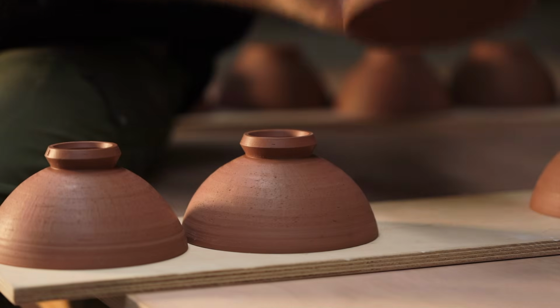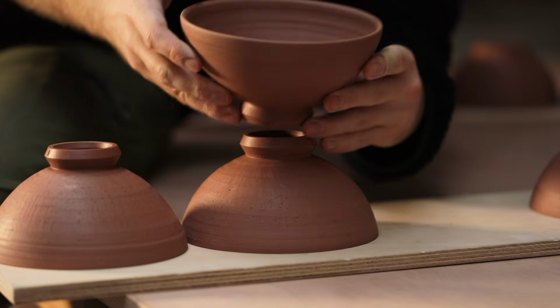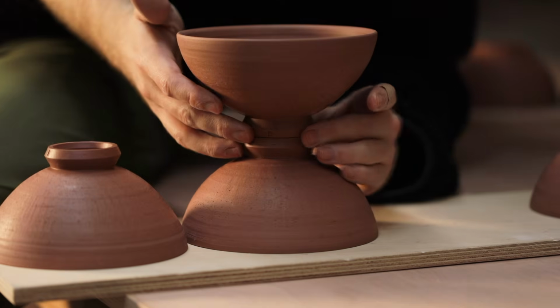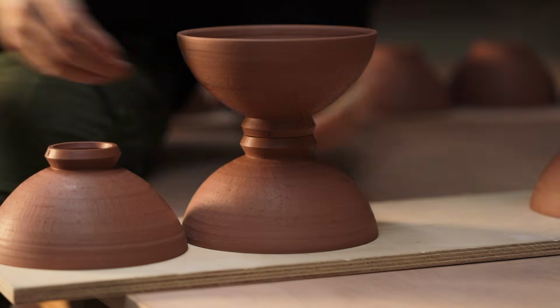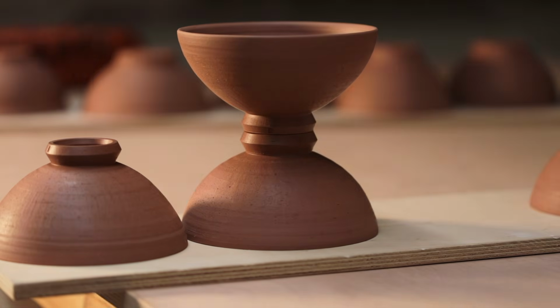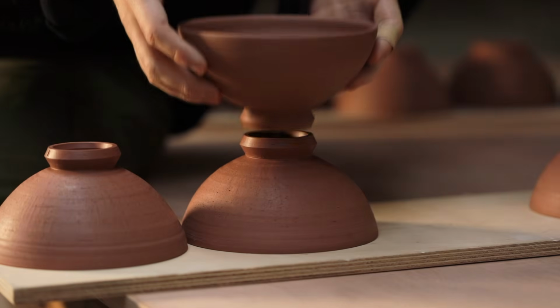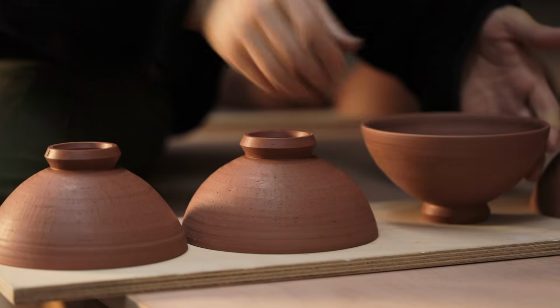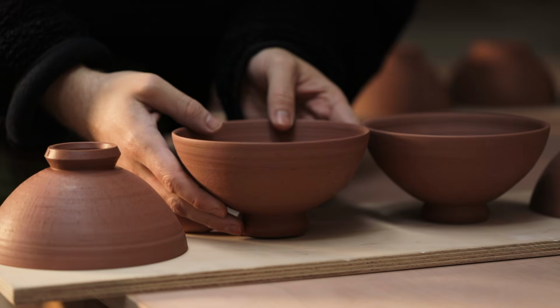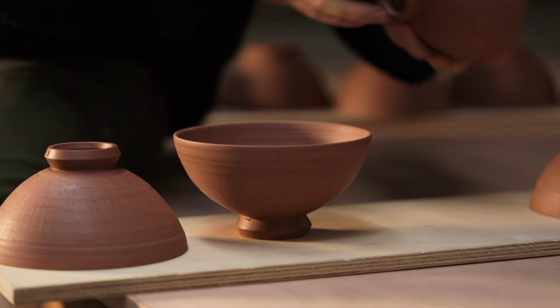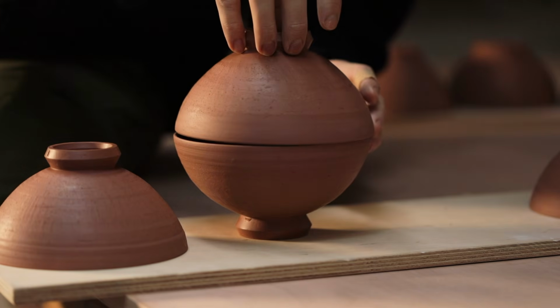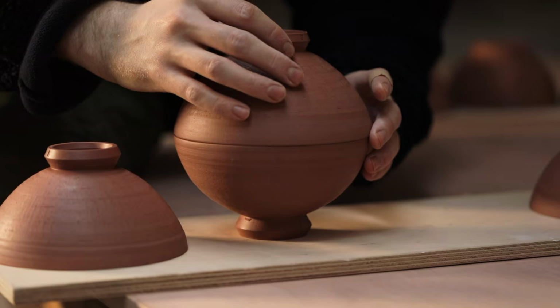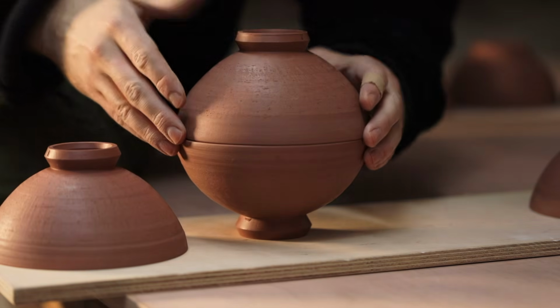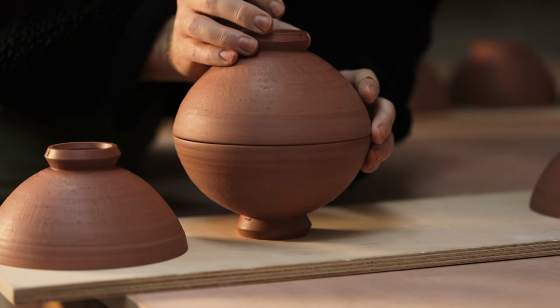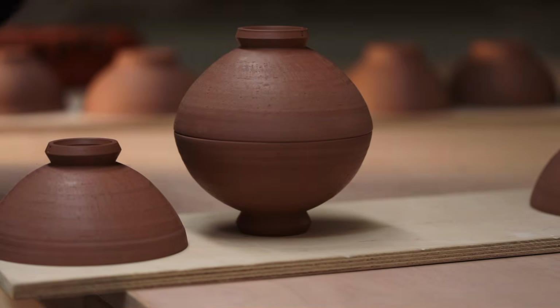They change colour as this happens, lightening in both tone and weight, and it's only once they're completely bone dry can they be packed into my electric kiln for a bisque firing to 1000 degrees Celsius. This first round of firing changes the pot forever. Up until this point, they can be recycled endlessly, but once fired, the pots will harden dramatically as a permanent chemical change occurs, and the pots become both stronger and porous, which is necessary for when the pots are dipped